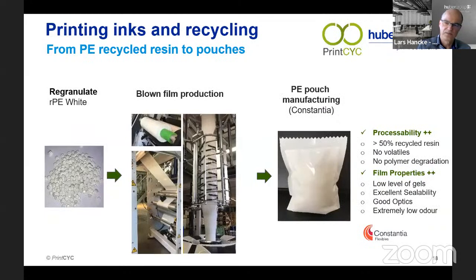And what has proven true for the polypropylene also worked out very nicely with the polyethylene. So in the technical facility of Constantia, we were able to convert the polyethylene regranulate into a blown film and to further convert that into a pouch, again with excellent properties with respect to organoleptics, odor, and to the shade and to the overall processability.